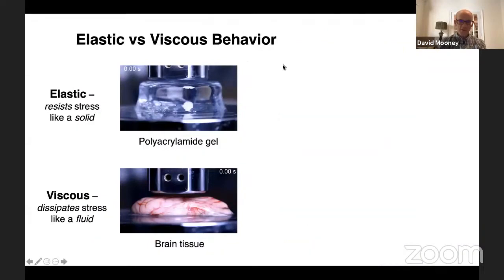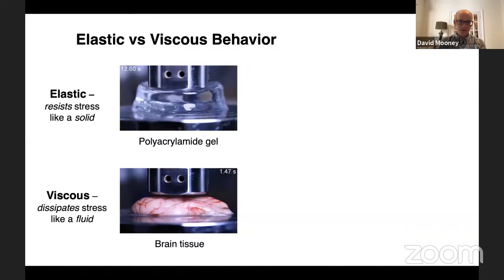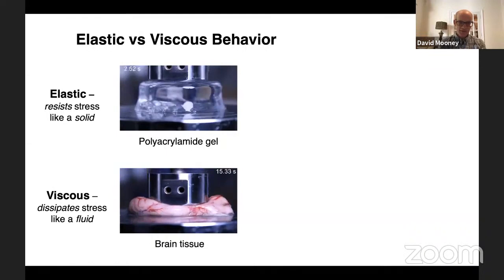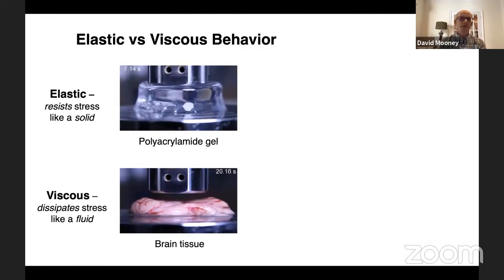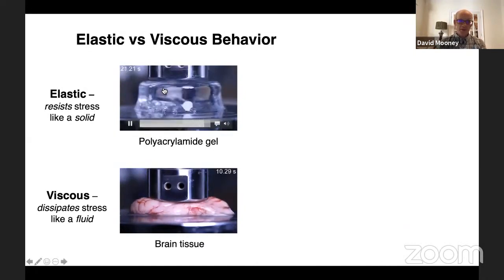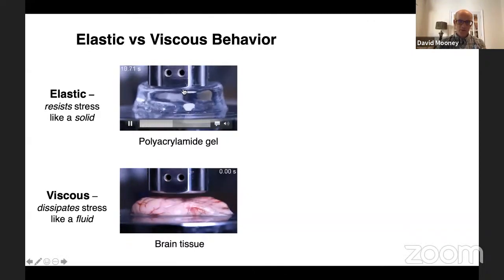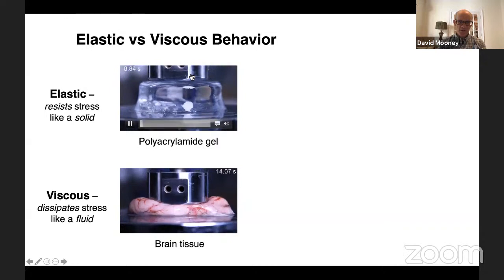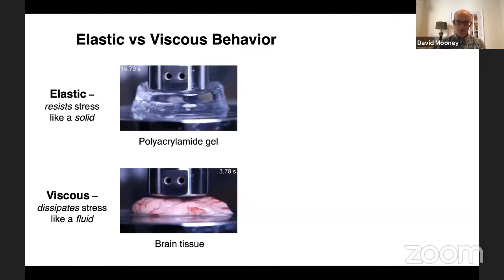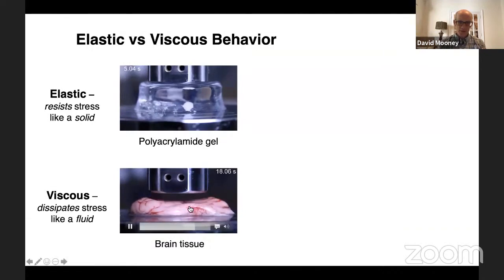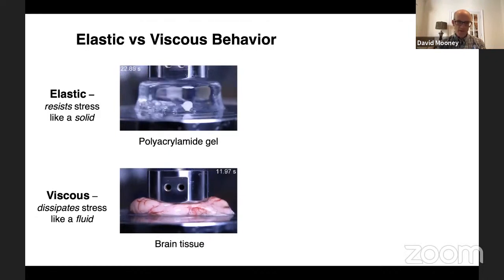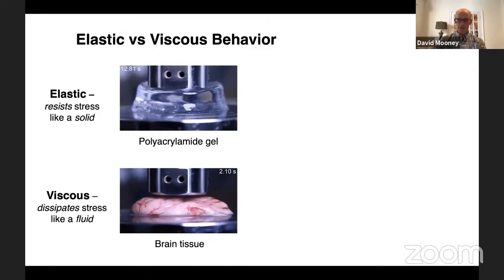Now, to give you a little bit of a visual sense of what viscoelastic and elastic materials are and how they differ, here are some videos of a purely elastic material being deformed on the top, a polyacrylamide gel, and a tissue, brain tissue in this case, being deformed on the bottom. And what you can appreciate from the material on the top is that as we basically apply a load, the material deforms, and then immediately upon release of the load, the material elastically and instantaneously goes back to its original dimensions. In contrast, with the viscoelastic material on the bottom, you'll appreciate that after we remove the load, some significant deformation remains in the material. So it's actually exhibited some flow. It's dissipated some of the energy that we put into it.